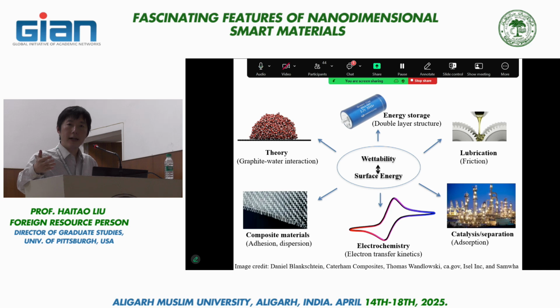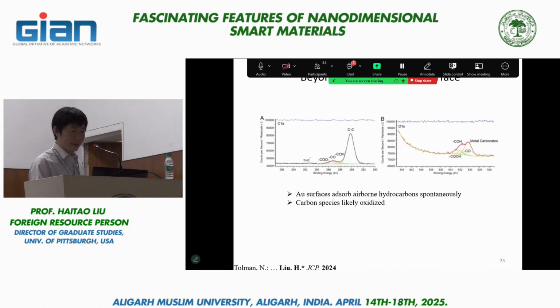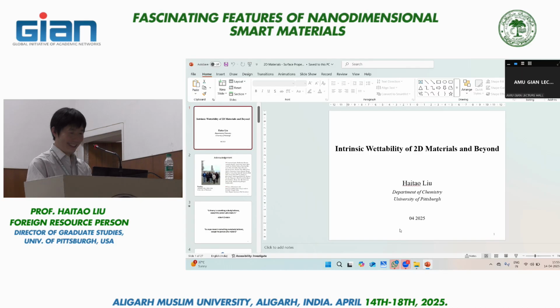Yes, this one. Okay. Sir, you mentioned here the water contact angle of clean graphite and dirty graphite. What is the meaning of those? Right. When I say dirty graphite, I mean graphite that has been exposed to air for an extended period of time, to the point that its surface has been covered by hydrocarbon. So in this context, the dirty graphite would be the graphite after 60 minutes of air exposure. So this dirty graphite is hydrophobic in nature. Correct. The hypothesis I would put forward is that everybody who previously measured wettability on graphite has been measuring on dirty graphite, where they found the hydrophobic behavior. But the intrinsic property would be much more hydrophilic.